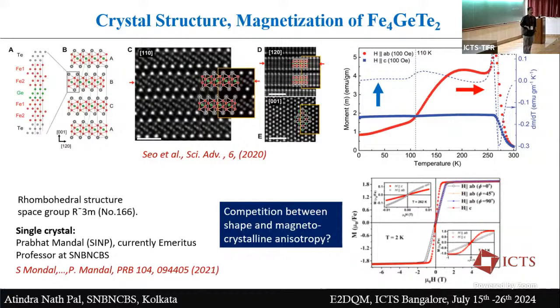That's what is probably happening. Sorry, I have a question. Yeah. This anisotropy, does it depend on the thickness? Yes, it should depend on the thickness. This temperature, will it depend on the thickness? It should depend. People have observed the spin reorientation temperature. Nobody has measured the anisotropy before, but what people have observed is that below 7 layers, spin reorientation has a dependence on thickness. But above 10 nanometer, it's fine. It has a weak dependence.